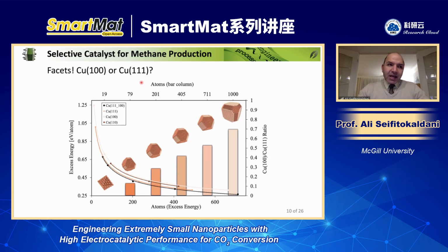So in our lab, we were interested to see what happens if we go further down and utilize very small particles. First of all, we had two questions. The first question was, what happens to the particles' crystallinity? Do we have more 111 at a smaller particle size, or more 100, or maybe other facets? So for that, we started DFT projects, running a huge amount of computations, and we created particles with different shapes at different sizes. So this was really a massive project.